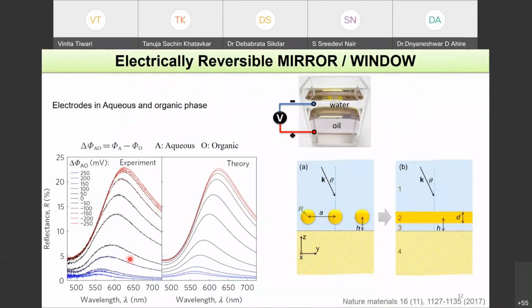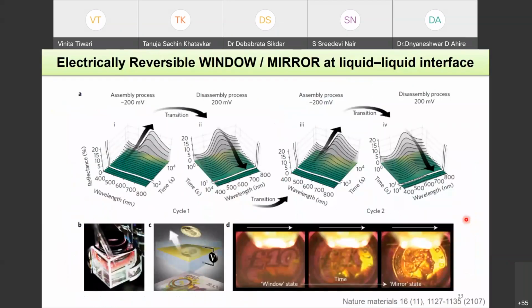And another interesting part is that by slowly varying the potential, you can also control the reflectivity of this mirror that is getting formed. And you can see we are able to predict this using both experiment and theory, and we understand how things work in this particular regime. So basically, when the nanoparticles are getting close to each other, they are forming a fictitious film of an effective permittivity, which is slightly different than gold, but that layer reflects very strongly. And you can repeat this assembly, disassembly process of nanoparticles many times, and you will see that they repeat the performance. So it's a very stable system.